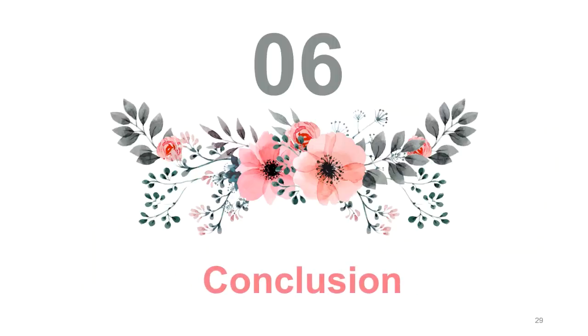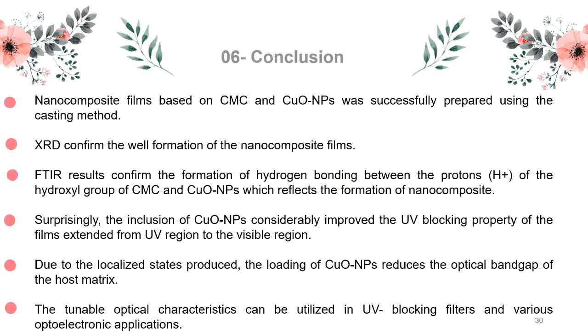Conclusion. Nanocomposite films based on CMC and copper oxide nanoparticles were successfully prepared utilizing the casting method. XRD and FTIR confirmed the formation of the nanocomposite films and the formation of hydrogen bonding between the protons of the hydroxyl group of CMC and copper oxide nanoparticles. The inclusion of copper oxide nanoparticles improves the UV blocking property of the CMC, extended from the UV region to the visible region. The localized states produced within the band gap of the CMC reduce the optical band gap of the CMC. The tunable optical characteristics can be utilized in UV blocking filters and various optoelectronic applications.